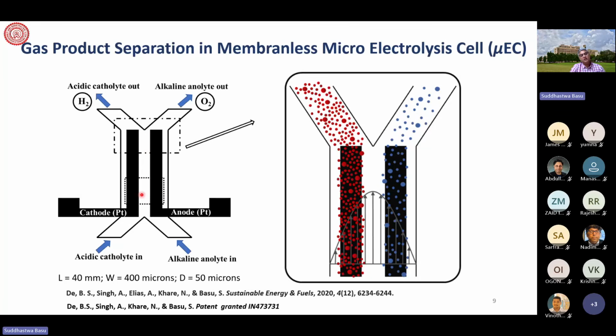and the movement, so that we can have a lesser open circuit potential requirement, because of the presence of the liquid junction potential, the easy movement of ions is possible, because ultimately H plus has to move and OH minus has to move in either direction, so that you can have the complementary reaction, which is the oxidation and reduction reaction, for the oxygen evolution and hydrogen evolution reaction to take place in the respective cathode and anode.